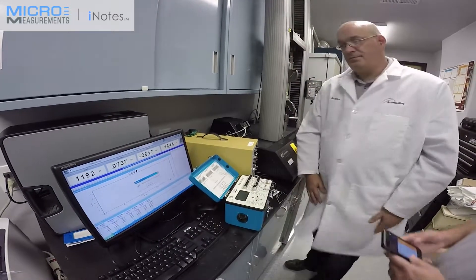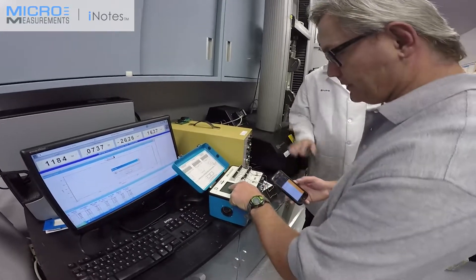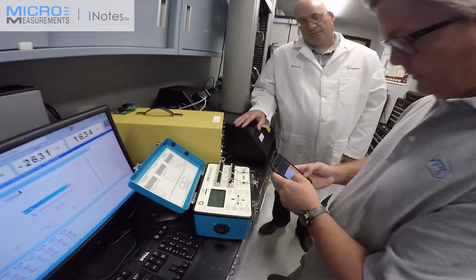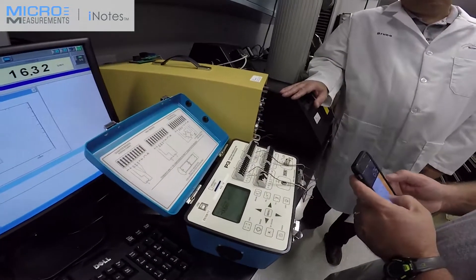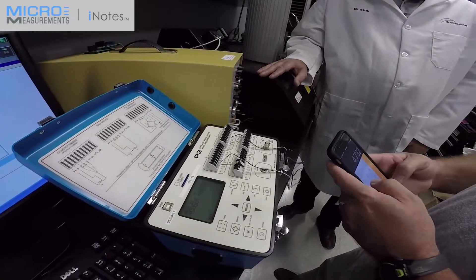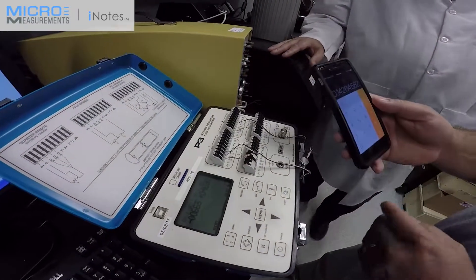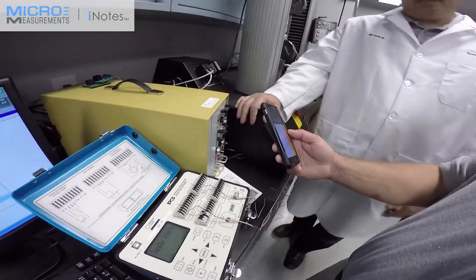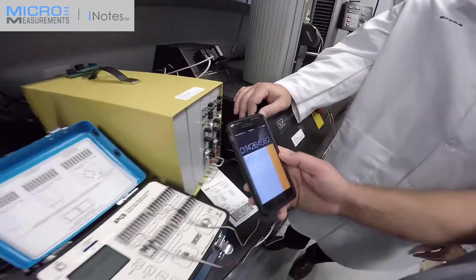We sure can. Alright, so let's hold it right there. So we've got 675, 4732. 675 divided by 4732. Yeah, so that's 0.1426. This is what we were expecting for this product.